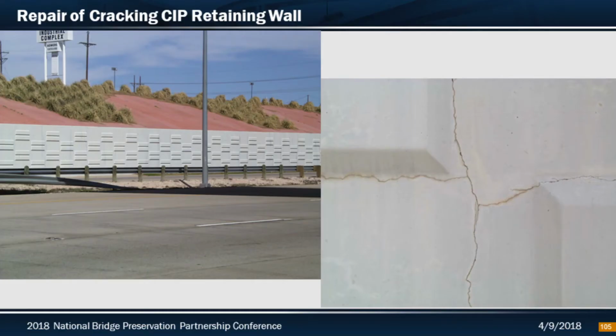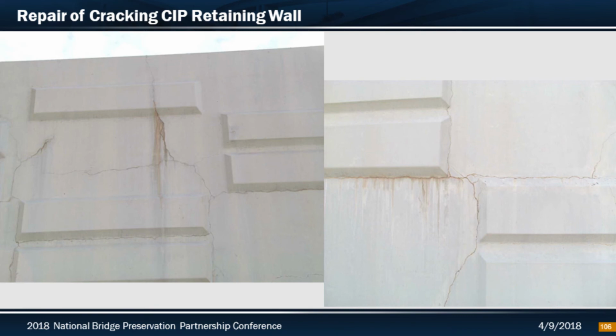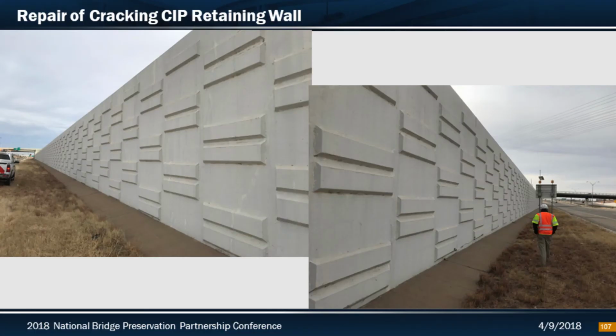Probably the final one here, this is the repair of the cast-in-place retaining wall, which was most likely more of a geometry issue with the design. I think it was a drilled shaft wall. Thickness of the wall changed, so there's a lot of early age cracking in the walls that could have potentially been a structural issue over time. The engineer wanted to go ahead and wrap it with 3 layers of glass fiber wrap, see what it would do. Here we are almost 18 years later.